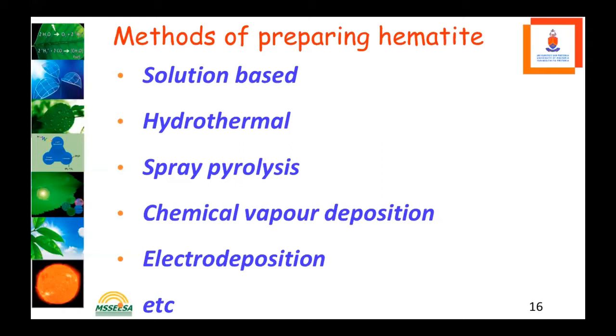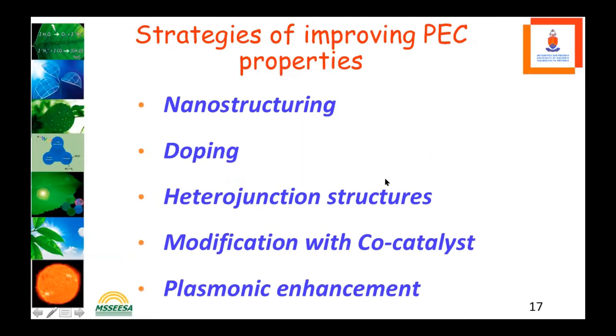So then we chose to focus on hematite, and there are different ways of making this hematite. Synthesizing it is solution-based, hydrothermal, spray pyrolysis, chemical vapor deposition, and electrode deposition. There are still many more. So the strategies to improve the hematite conductivity have been nanostructuring. Many people have spoken about nanostructuring, doping of the material, forming the heterojunction structures, using the very material that has been spoken about in slide number 11. For example, we have made a heterojunction structure of copper oxide and hematite, and we have seen the photocurrent improved.